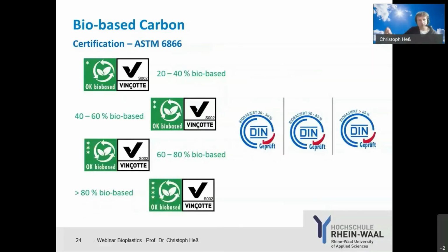Similar to biodegradation and composting, and that is the final slide, we can certify these bioplastics according to their bio-based carbon share. The standard is an American standard, ASTM 6866, that is widely used. And again, we have, for example, Vinçotte as certification body, today that is done by TÜV Austria. They have introduced this system, called OK Biobased, so not OK Compostable, but OK Biobased. And then they provide 1, 2, 3, or 4 stars to the material. So for 20 to 40% bio-based carbon, 1 star; between 40 and 60%, 2 stars; 60 to 80%, 3 stars; and more than 80% bio-based carbon, we have the 4-star bio-based label that we can ask for, and we can certify our material.